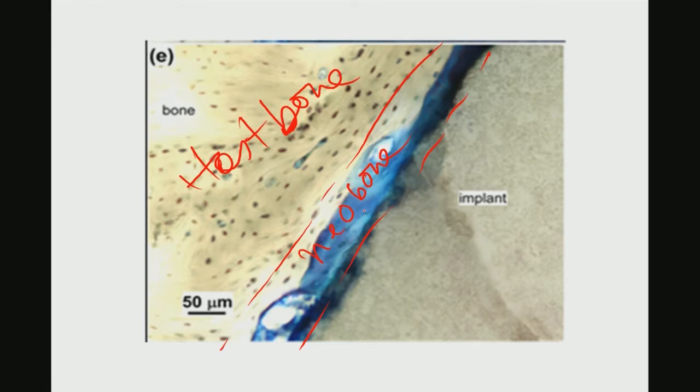Now, what I mean by BMD, bone mineralization density, is that once this bone starts forming around the implant or in the small cavity around the implant, this bone may not be mature enough at different time points of the implantation. Mature bone means bone which, composition-wise or property-wise, is to some extent similar to the host bone, and will have bone mineralization density equivalent to that of the host bone. But during the process of bone maturation, this bone mineralization density increases, and that is exactly what happens in this particular case.